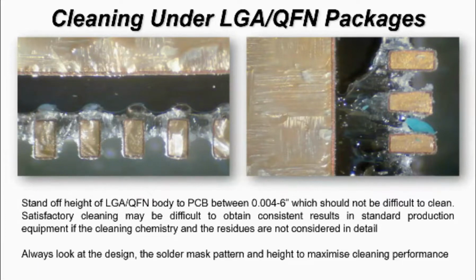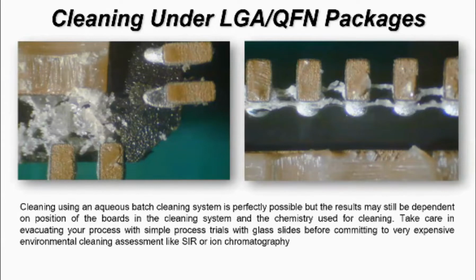within the solder joints. Now, most people don't clean QFN LGA packages, but they can be cleaned. Here's an example of inability to clean, but understanding the cleaning chemistry and its compatibility with whatever flux material you're using is key to effective cleaning. Those two things. It's not the power of the machine. It's not the solubility of the material. It's not the cleaning performance of the raw cleaning material. It's that combination and getting that right. So in this particular example, as you can see, poor performance. And in this example, again, poor performance.